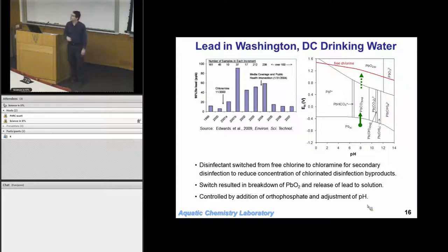If you have free chlorine, you have PbO2, that is lead in the plus 4 oxidation state, which is really unusual to find in a natural system. Drinking water distribution system, I would say, is not really natural, but it is in contact with natural water. So what you have done is gone from a solid through a dissolved species up to another solid species. So the lead pipe, which is the pipe that might connect your house to the water main, was elemental lead. But if you have free chlorine, that elemental lead could be converted over to lead 4. A solid.